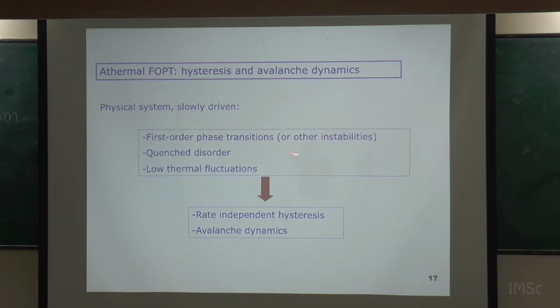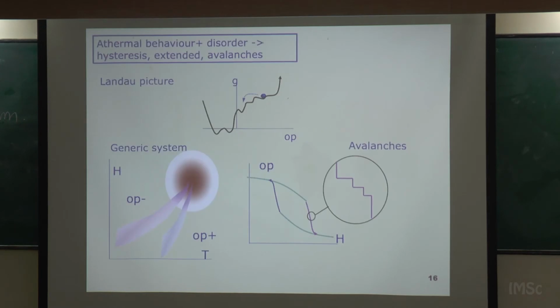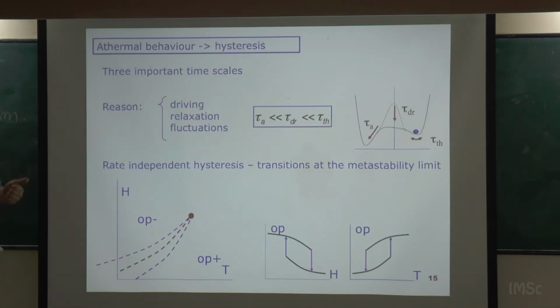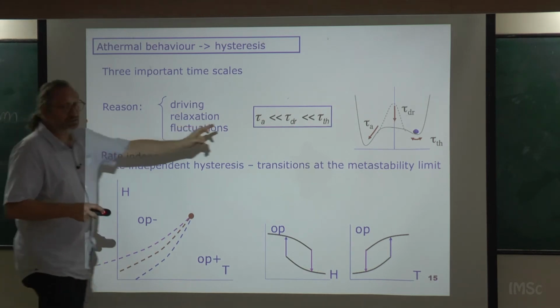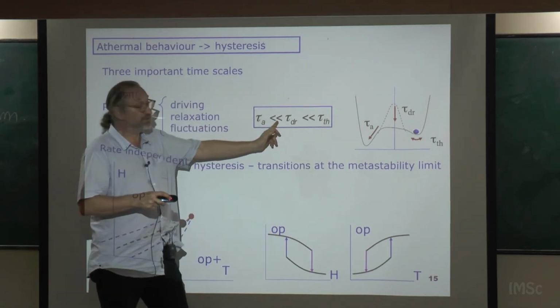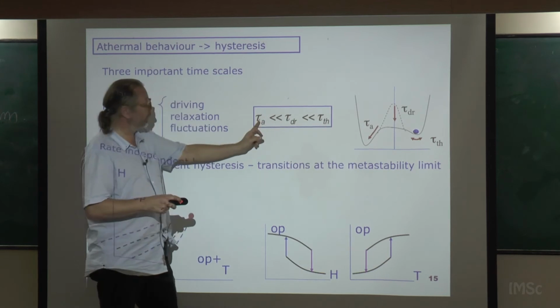And in this case, then, we can justify the existence of two things. One, rate-independent hysteresis, this kind of hysteresis that you see here, this kind, or even this kind of hysteresis, is rate-independent in the sense that if you change the rate, if you don't hit this value and you don't hit this value, the curve will be the same.